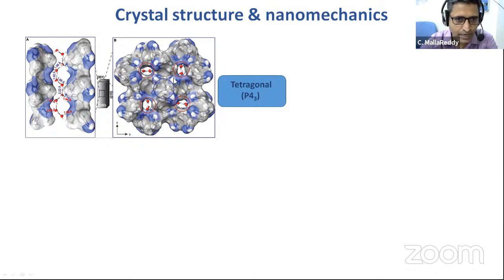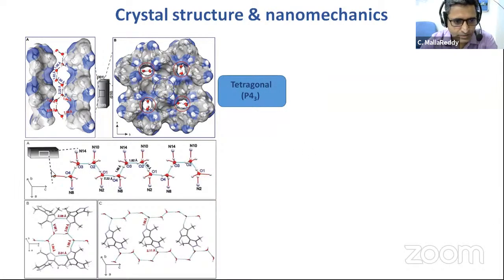And then you also have hydrophobic groups, because you have four methyl groups on the molecule. All these hydrophobic groups come together and form hydrophobic zones. And then you have hydrophilic zones where you have strong hydrogen bonding interactions. So you have a three-dimensional hydrogen bonding network, because these bipyrazole molecules are also attached to this water chain, and they are all connected through hydrogen bonds. But in between, you have hydrophobic regions formed by these methyl groups. So this makes it special. These are the water chains where you can see different hydrogen bonding interactions.